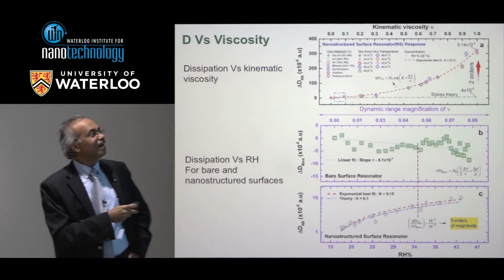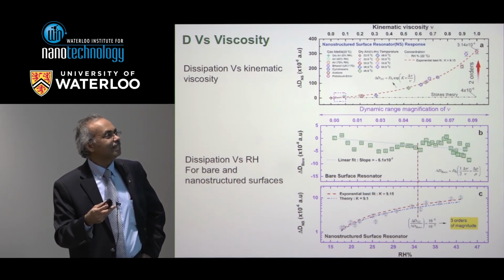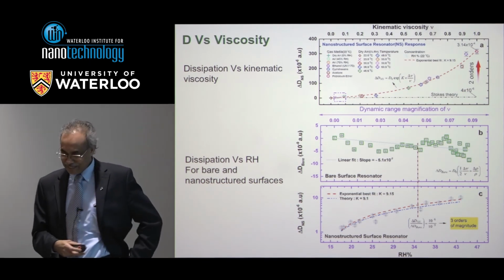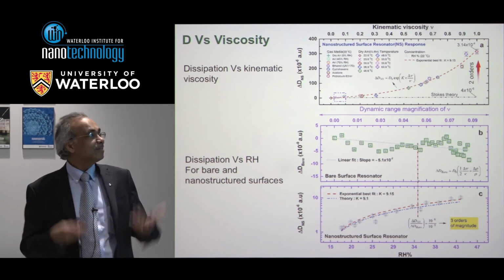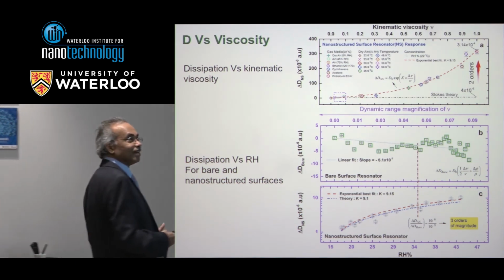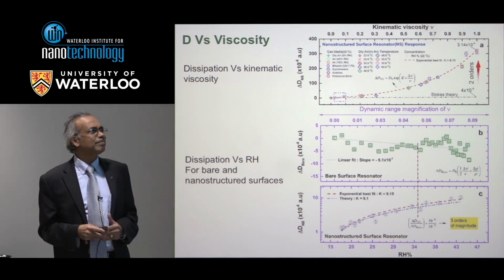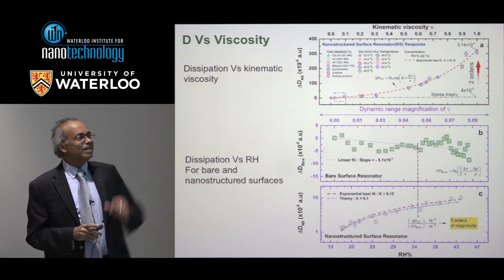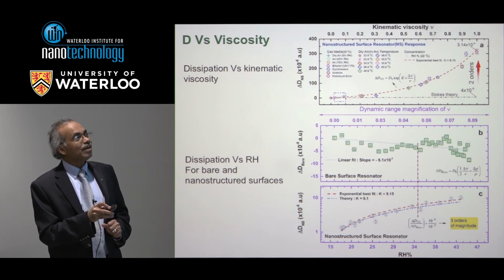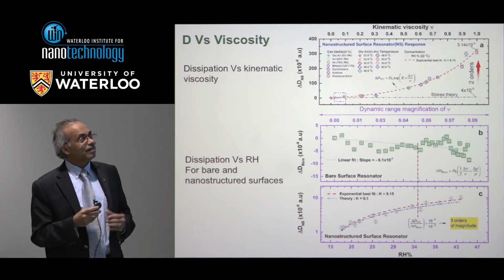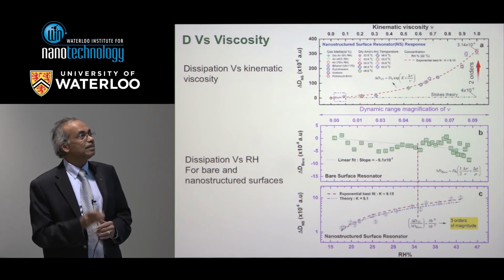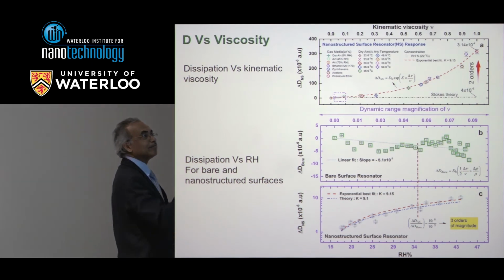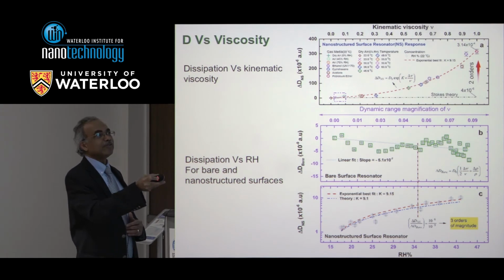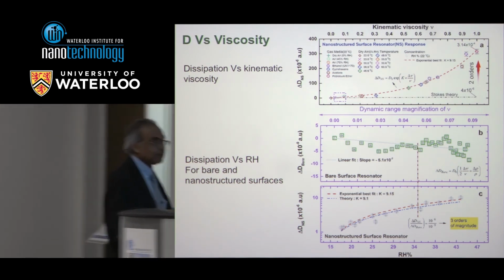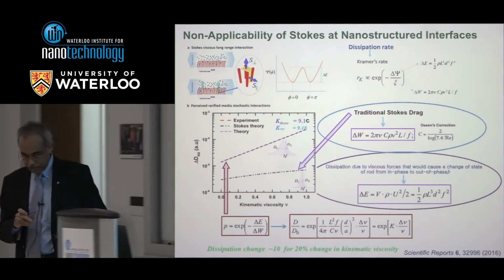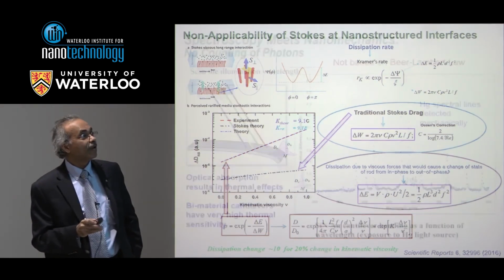So we started using that, basically looking at the viscosity. Nobody uses viscosity for sensing because it's practically a useless parameter, unless you are using oil sands or bitumen or something like that. Most of the time, viscosity is not a good indicator for materials. But if you can enhance the dynamic range of the viscosity at a given temperature, and that's what we are doing here with the nanostructures, then viscosity itself or dissipation itself can be a good sensing parameter.